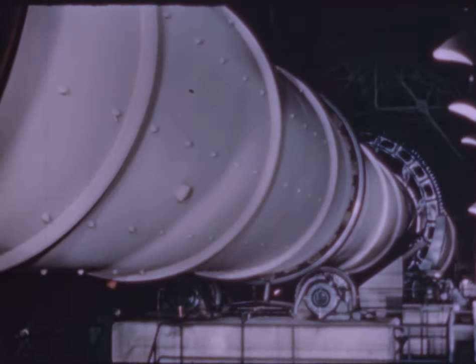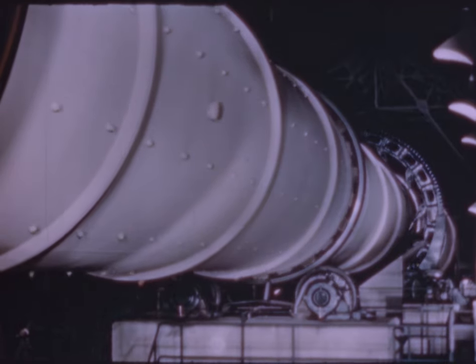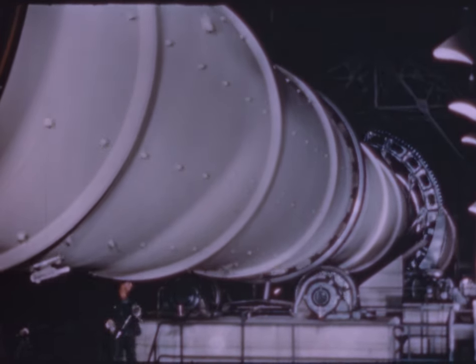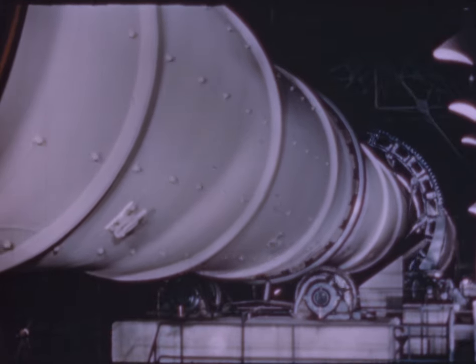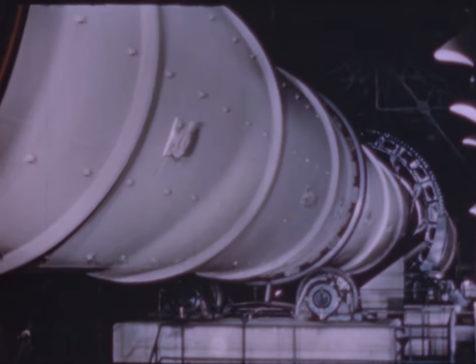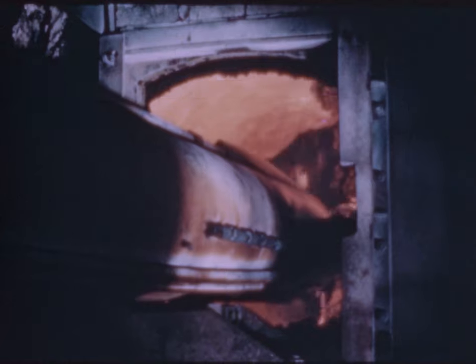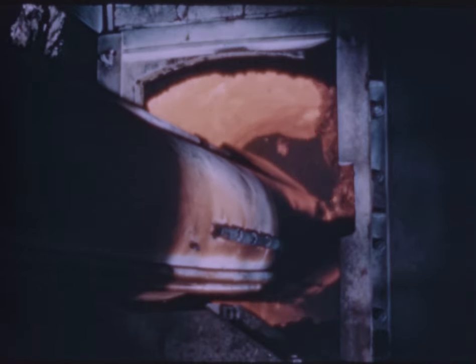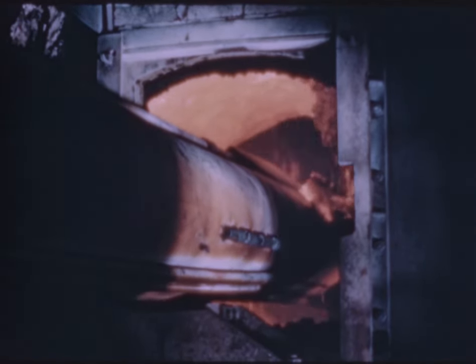This 270-foot rotary kiln was designed for processing manganese concentrates derived from the rhodochrosite ores of Butte's mines. On entering the kiln, the concentrates are first dried. As they approach the gas burners in the lower end, they release carbon dioxide. As the sintering zone is entered, with a temperature of 2600 degrees Fahrenheit, a nodulizing action takes place. The sticky mass rolls into balls, or nodules, but some of it also adheres to the walls of the kiln and is removed by a giant boring bar.